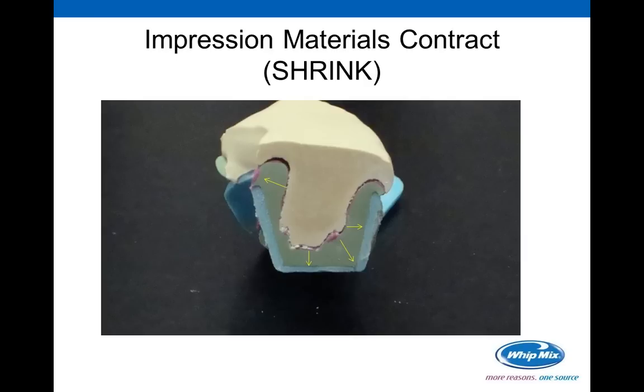Now, if they've not used some kind of a tray adhesive there, you've all seen this. When the contraction takes place, the impression material pulls away from the tray. You cannot overcome that pulling with an expansion of a die stone, or even by pushing it back. It's already damaged itself, and you should have the doctor redo that impression. I've heard it said before, in many instances, that you should match the expansion of your stone material with the contraction of your impression material.